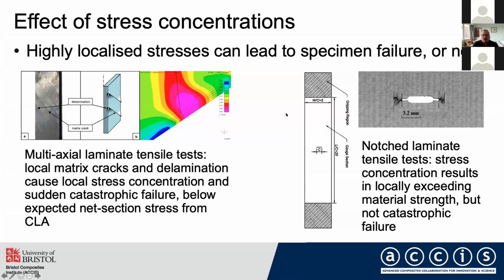So I just want to particularly touch on a few different cases from our work at Bristol, where variable effects can be observed, particularly as one moves up the length scale. So if one looks at laminate or coupon level tests, I've got two examples on the screen here, both of which have localized stresses. On the left-hand side, it's a multi-directional laminate where locally one gets a bit of surface matrix cracking, and that surface matrix cracking leads to some small corner delaminations at the intersection between that matrix crack and the free edge. And as you can see from the FE analysis, we get a local stress concentration, and that stress concentration then becomes high enough to influence the overall failure of the specimen.